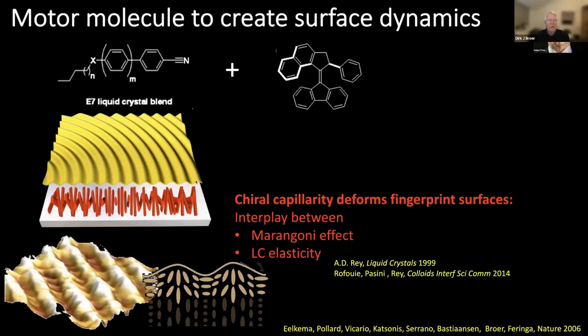Well, this fingerprint alignment, because of the chiral capillarity, forms deformed surfaces, as is shown here. And first of all, we have the Marangoni effect, the effect that the chiral molecules have a lower surface tension in the perpendicular orientation than in the planar orientation, which makes that you have some material flow to the locations where you have perpendicular orientation, that is also shown here, which then builds out a little bit in comparison to the areas where you have your planar orientation.